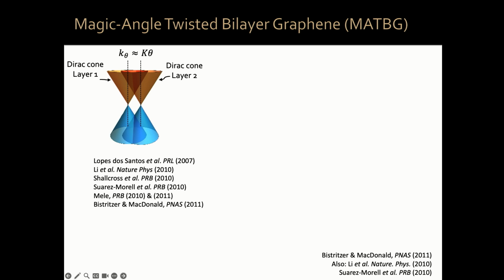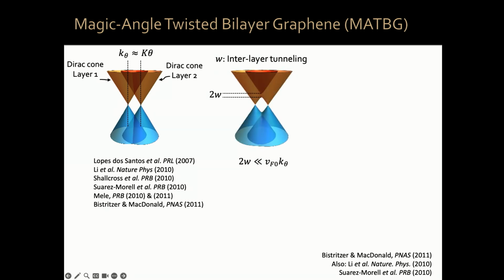However, because when I put graphene on top of graphene, these are just 3 angstroms apart, the electrons are very much aware that the other graphene sheet is there. In particular, they can tunnel back and forth between the two graphene sheets, quantum mechanical tunneling. So this interlayer tunneling leads to a band repulsion at that crossing point. This is the exact same thing as bonding and anti-bonding states in a hydrogen molecule, but this is bonding and anti-bonding bands in a giant graphene molecule. So that crossing point opens a gap and pushes the band to lower energy.